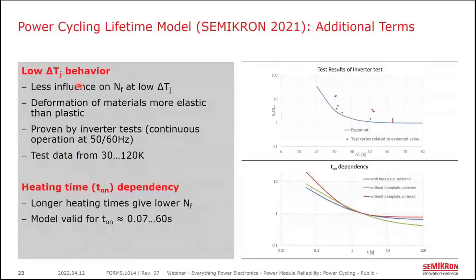And if you plugged in that 5 or 10 degrees Kelvin with the 50 or 60 hertz rate, you plug that into the older LESIT model, you might find that the module would be predicted to wear out after just months of operation because you're racking up 50 or 60 temperature swings every minute. But we know from fixed frequency motor drives that have run for years, decades in the field, as well as from lab experiments, that this is just not the case.